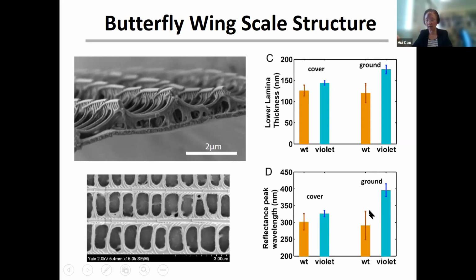That's why we see the violet color now. Actually, this thickness change is only about 50 nanometers. That seems like a very small amount, right? But it is actually a lot, because the thin film itself is a little bit more than 100 nanometers. So the wavelengths can be shifted about 100 nanometers. That can really change the color a lot.